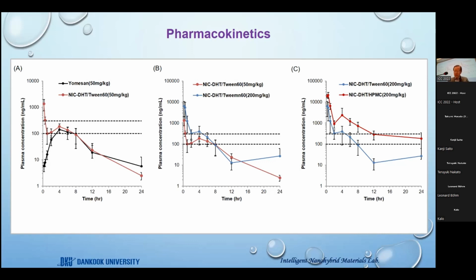So on the right-hand side, we attempted to further optimize the PK profile of the oral formulation. NIC DHT surface was coated with hydroxypropyl methylcellulose, which has a gastrointestinal retentive property. The PK profile of NIC DHT HPMC drug shows that the niclosamide plasma concentration above IC50 was sustained until 24 hours. And based on the IC100 value, niclosamide plasma concentration lasts for 12 hours here, which is the champion data ever reported so far.